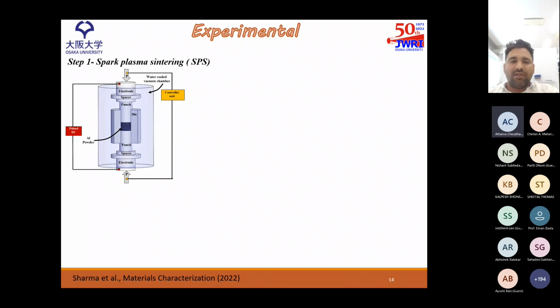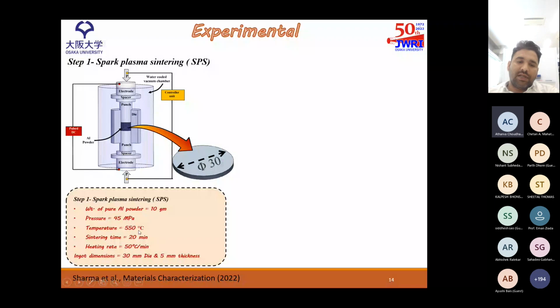So we came up with a solution to combine spark plasma sintering with friction stir processing. In the first step we did the spark plasma sintering, and we obtained a powder billet with a 30 millimeter diameter and 5 millimeter thickness. And these are the process parameters we have used. The most important parameters are the temperature, around 550 degrees centigrade, and the sintering time, around 20 minutes. And we have produced this billet.